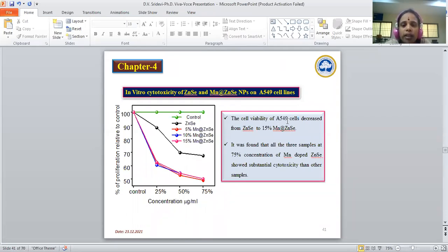It was observed that A549 cells decreased progressively at a low dosage from zinc selenide to 15% manganese doped zinc selenide nanoparticles. It was found that all three manganese doped zinc selenide samples at 75 microgram per ml concentration show substantial cytotoxicity compared to other samples.